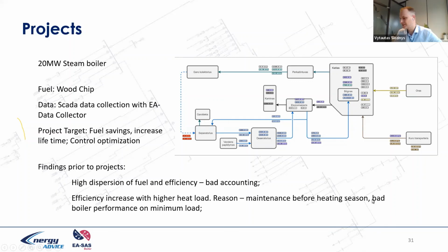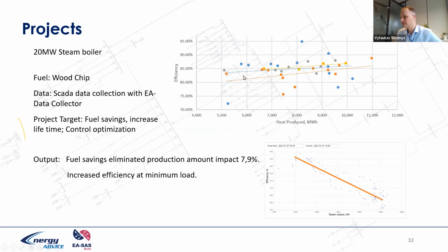The reason was maintenance before the heating season, bad boiler performance at minimum load, but we found that efficiency and high dispersion increased with heat production increase. So finally we did it like it should be: efficiency decreases to some minimum at the highest thermal load, and increases with a lower load. So a curve like this was created, as two curves of how it should be.